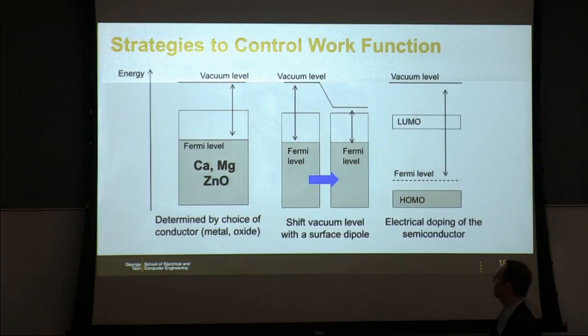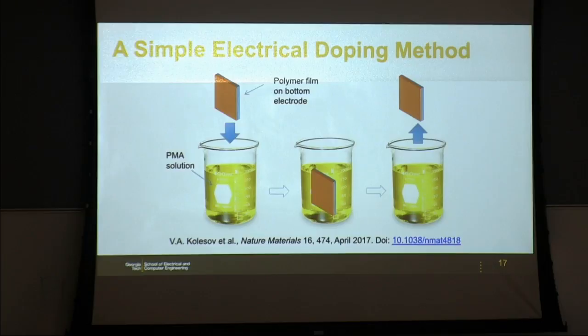And so next, I will give you an example of electrical doping as a way of producing low work function electrodes. And fortunately, these two techniques lead to low work function materials that are far more stable than if you build devices with electrodes that are made out of calcium or magnesium. Okay? So that's very helpful. So traditionally, if you take silicon, for instance, the way silicon solar cells are manufactured, they rely on a p-n junction. So you start with a p-type piece of silicon, and then you fabricate an n-type layer on top in order to make your junction.